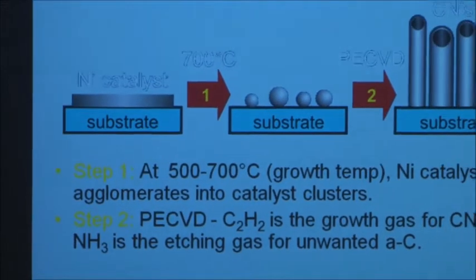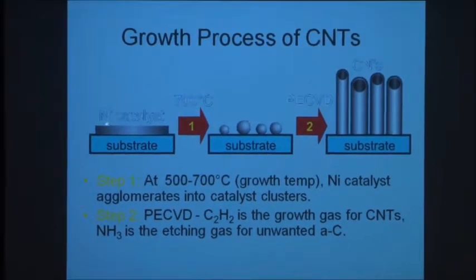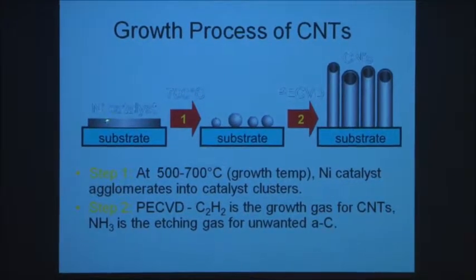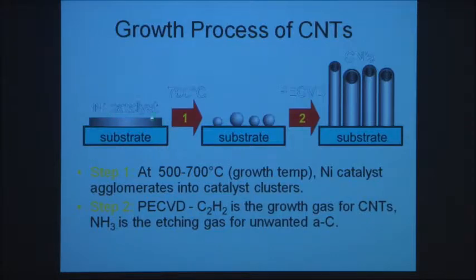The way we choose to do it, and the way most other people did in the end, was to look at catalytic chemical vapor deposition, which is based on heating up carbon-containing gases and decomposing them into the nanotubes, as we'll go into in a second. So here's a cartoon of a typical growth process. You can use a few different catalysts, but it is catalytically driven. So you need something like a nickel catalyst or cobalt or molybdenum, something like that, that will help drive the growth.